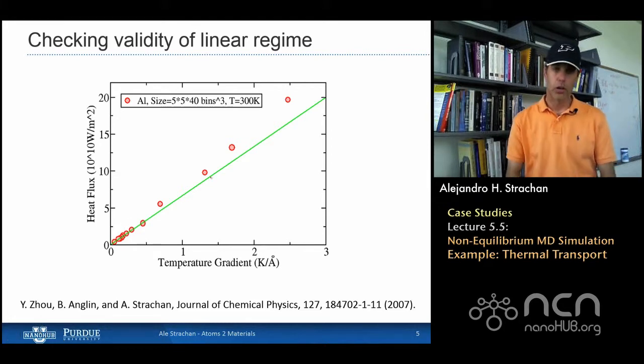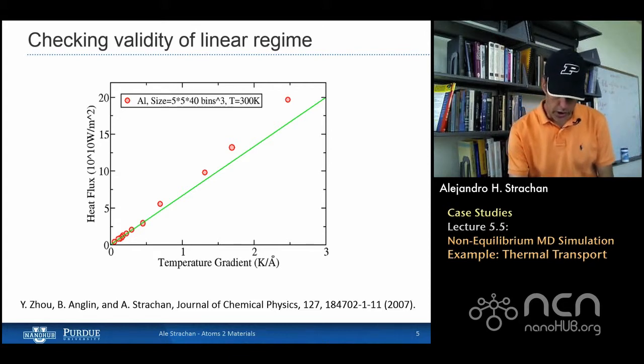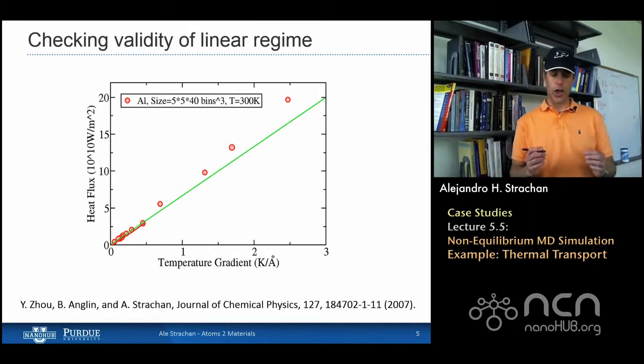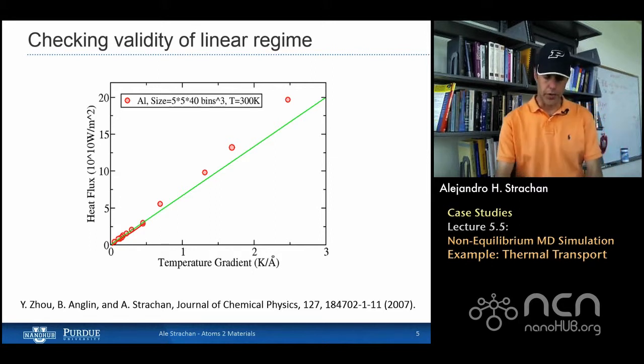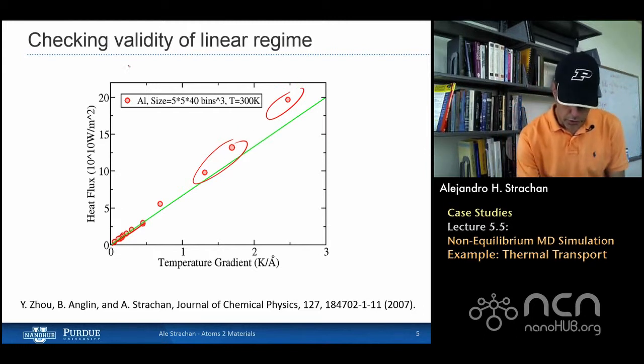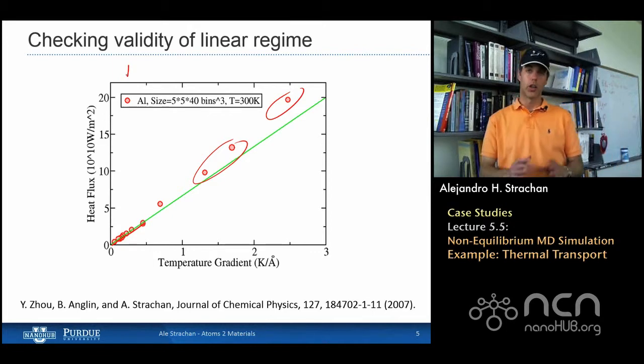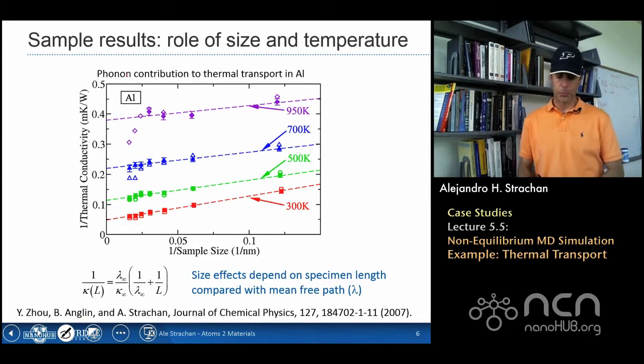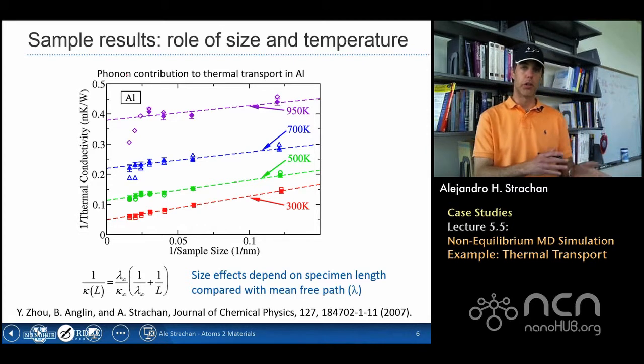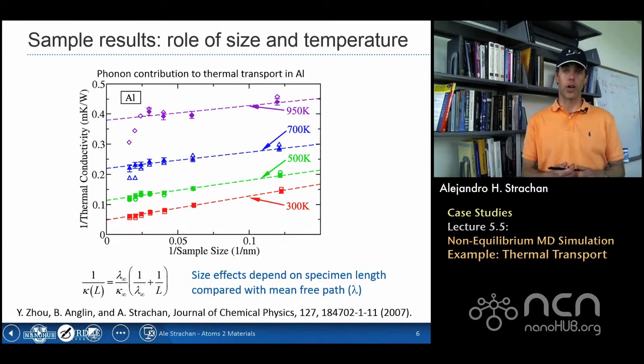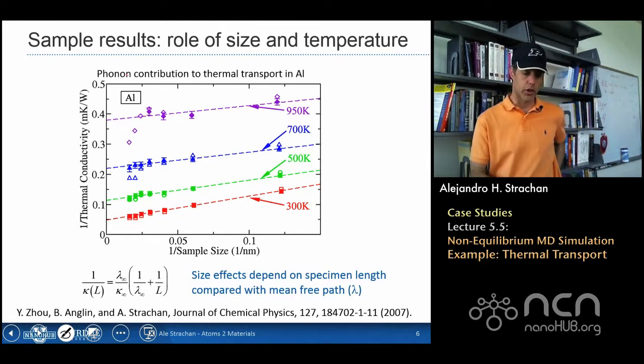Okay, you can see here what we're plotting is heat flux as a function of temperature gradient. You can see that these are all MD simulations. You can see that for low heat fluxes, we have linear behavior. For the larger heat fluxes, we start deviating from this linearity. This is phonon transport in aluminum, okay? Just the phonon transport in the metal. Now, let's talk a little bit more about other results that exemplify what MD can do in thermal transport.